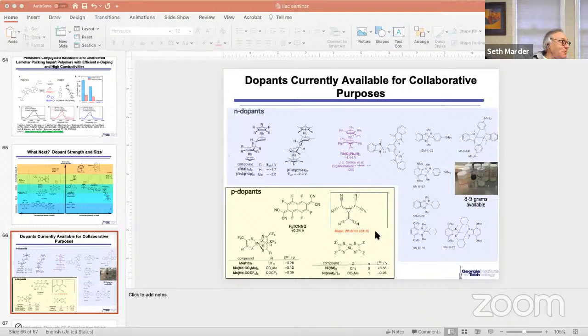But for example, if you want to have a film that you only dope at the interface and that you don't dope throughout, could be advantageous, okay? And then the issue of the solvent, it depends. I mean, the solvent is not going to, in the final analysis, necessarily determine where everything ends up thermodynamically, but it will have a large impact on the kinetics, okay?